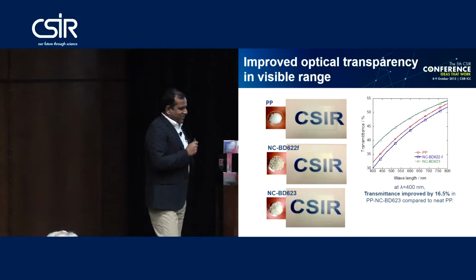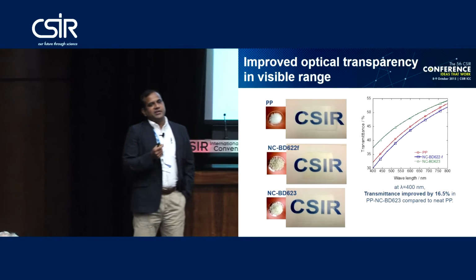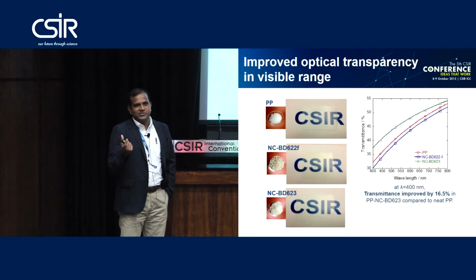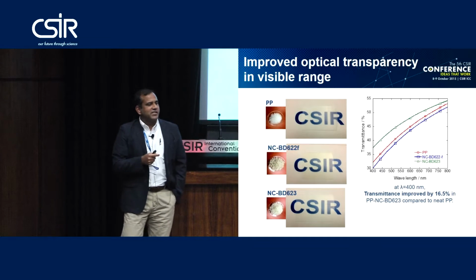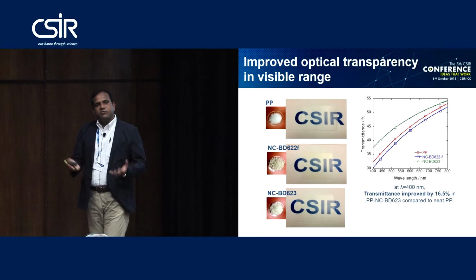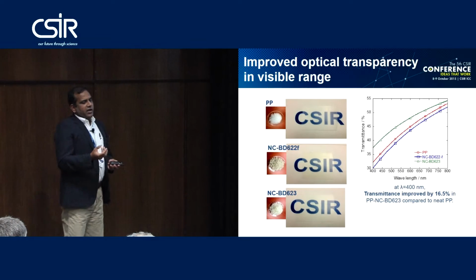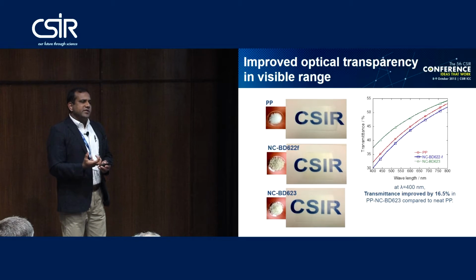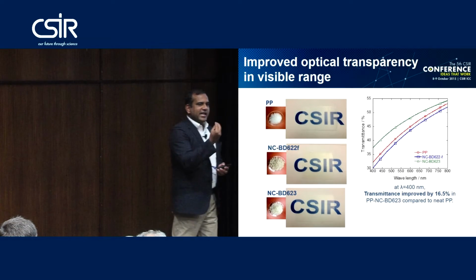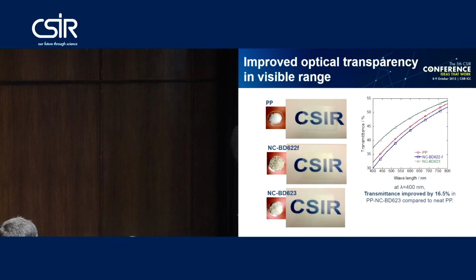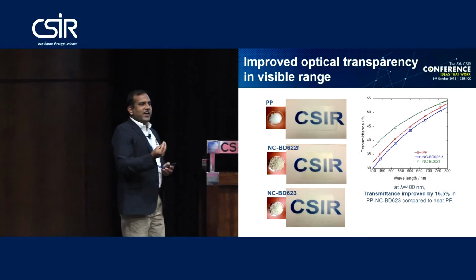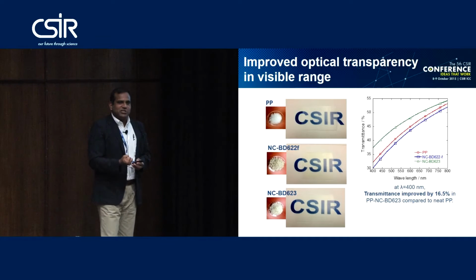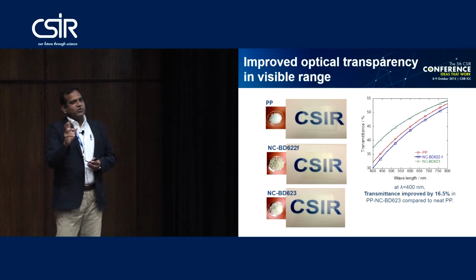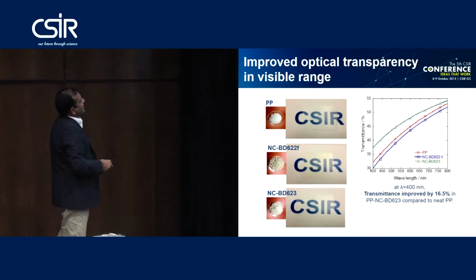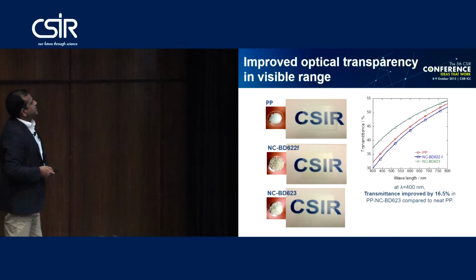So what is happening? Because you are getting nanoclay dispersion, nano level dispersion, and that is beyond our visible region, it will not disturb the transparency. But also, nanoclay particles act as a nucleator of the polymer matrix. So the nanoclay particles at the nano level dispersion help the polymer macromolecular chains to crystallize at a very small scale. Previously the crystal size was much bigger. Now, because of the nucleating effect, you are getting much smaller crystals, and smaller crystals do not disturb within the visible range. So you can see that when you add the clay to polypropylene, you get much better transparency.